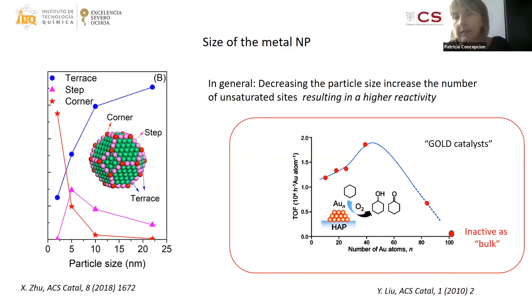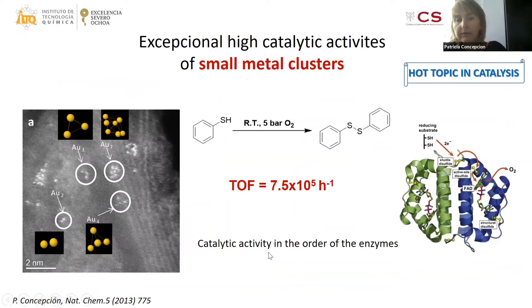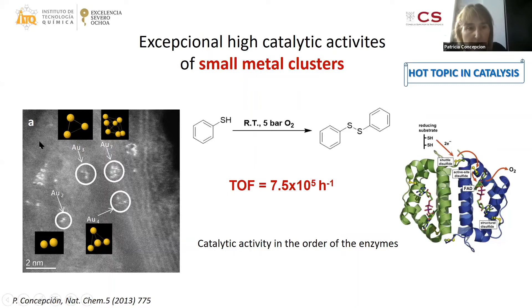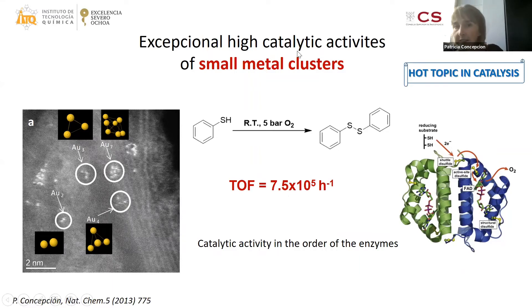In a very exciting work performed in our group, in the group of Professor Corma, we found catalytic activities in the order of enzymes when gold appears as small clusters composed of few atoms — clusters of three, seven, or four atoms — which have extremely high activity. This high activity of small metal clusters and even single atoms is nowadays a very hot topic in catalysis with really important industrial applications.